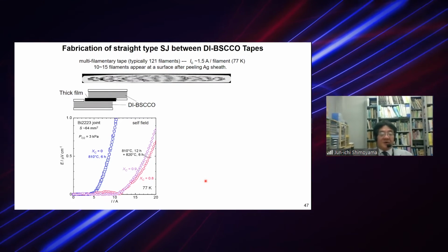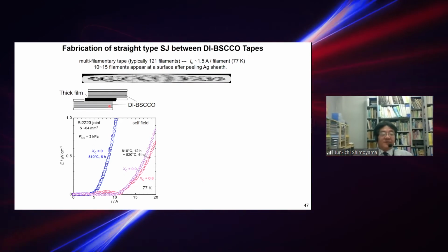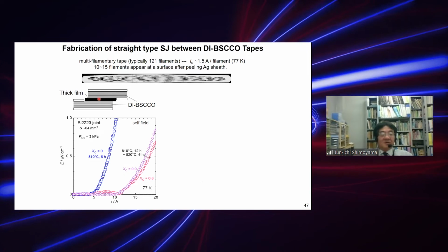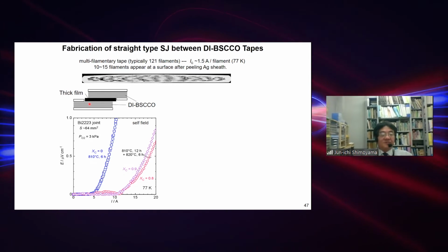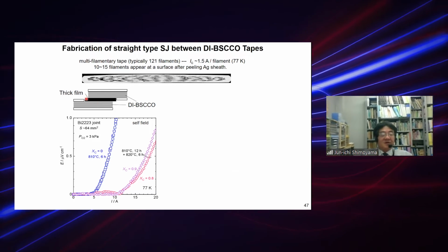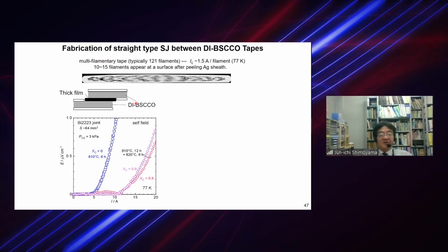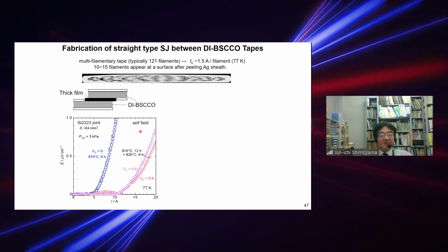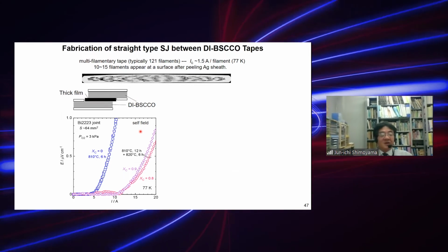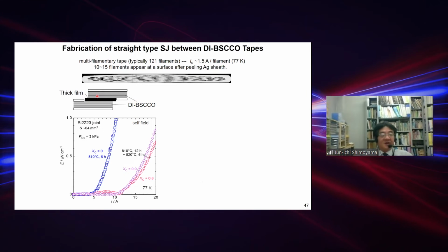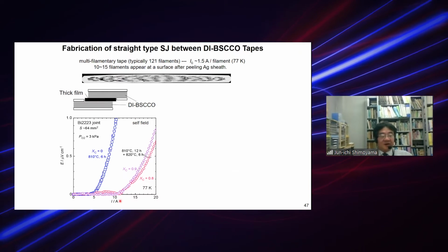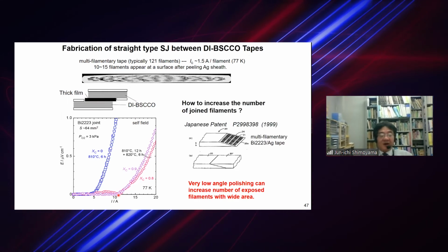So at the beginning, we prepared the superconducting joint, as you see here, only on the top surface of the multifilamentary wires. This is the intermediate layer. But in this case, only 10 or 15 filaments out of 121 filaments are connected by this layer. The critical current is very low, only 10 amps.